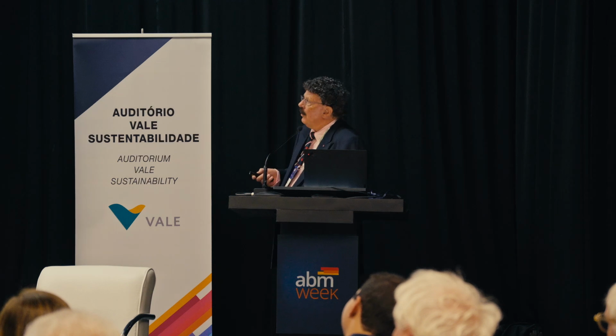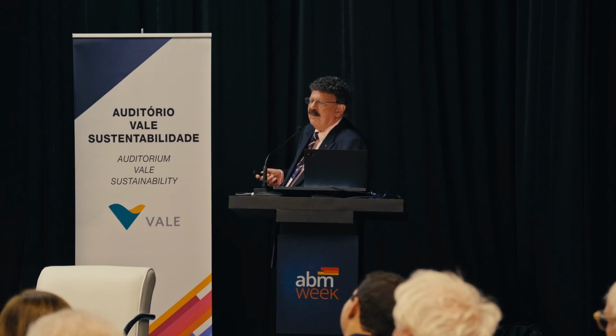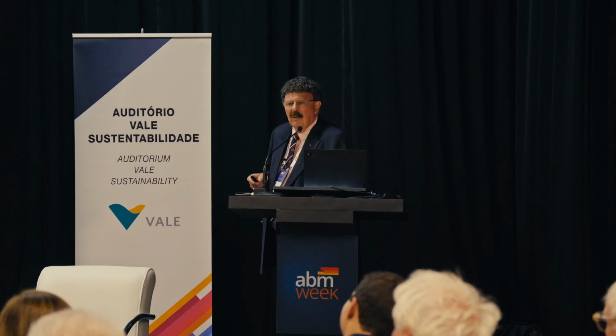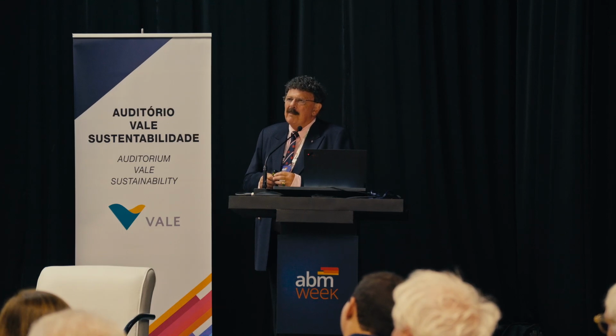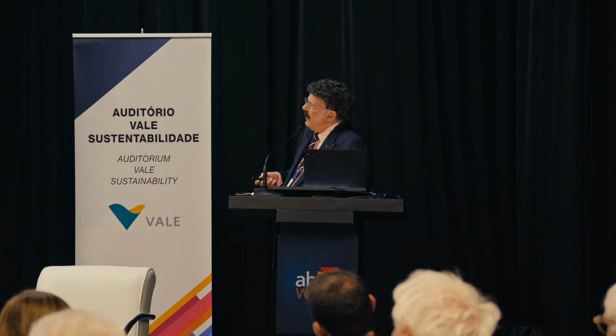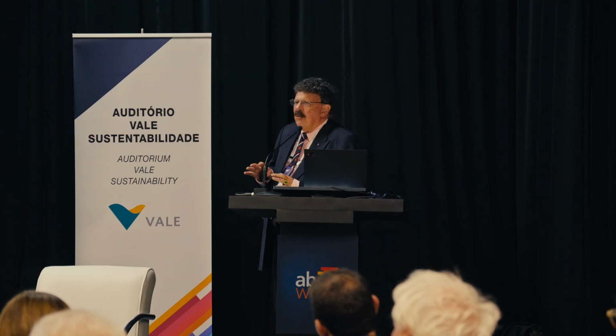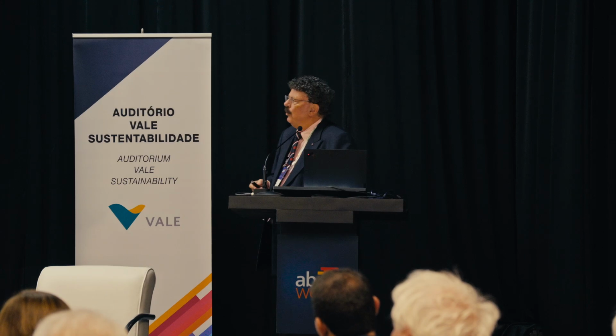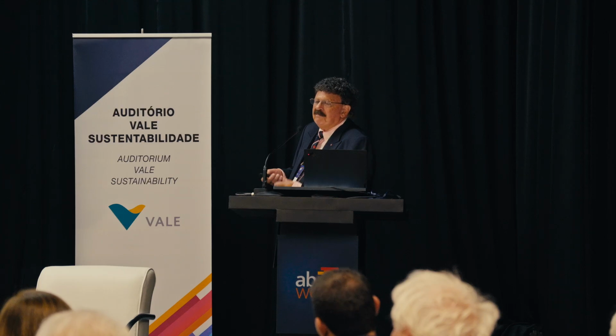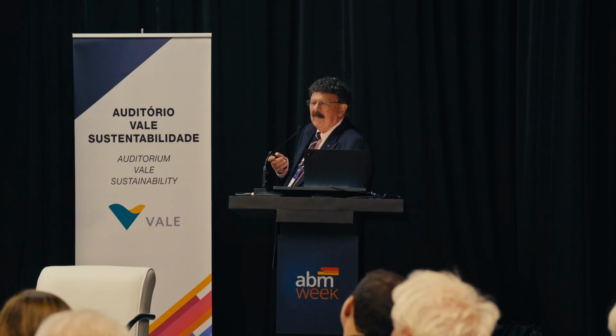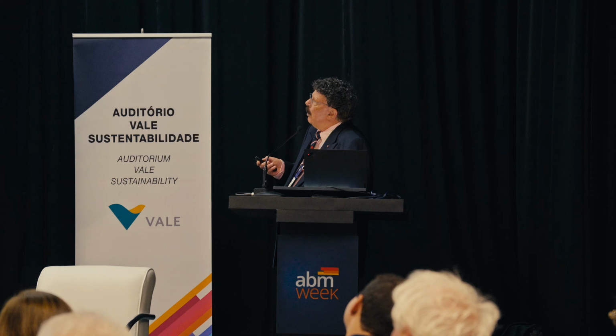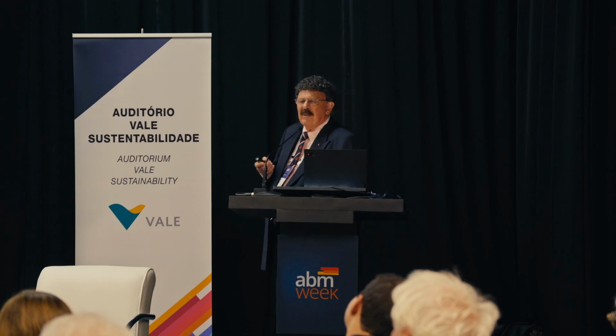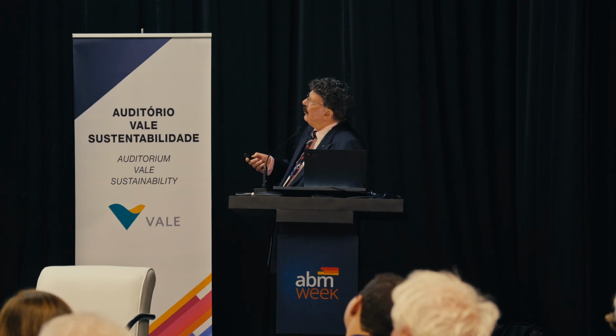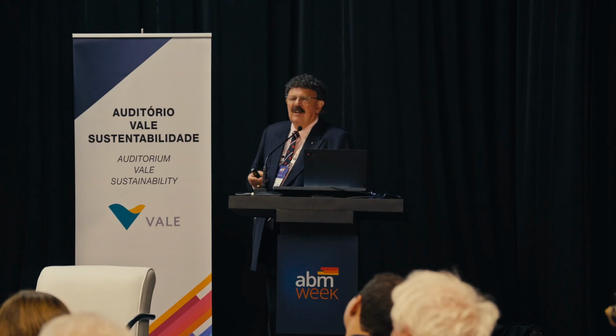Just let me end with this. These alloys, there's a number of things going on here, I haven't explained them all, but these alloys have asymmetric dislocation cores, which tend to promote more than one slip mechanism. And so we think that's an important thing. The group 4 elements lower the unstable stacking fault energy. That's a toughening mechanism too. And we've done simple fracture initiation models with atomistic simulations. This is the Rice-Thomson mechanism for ductility.